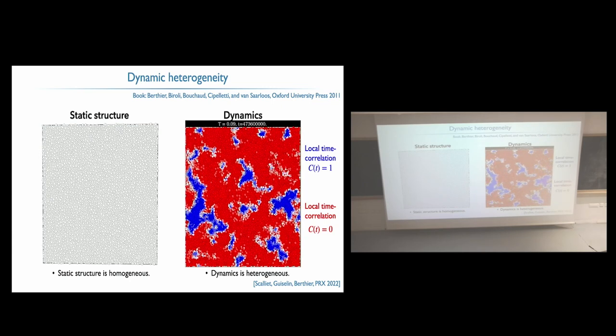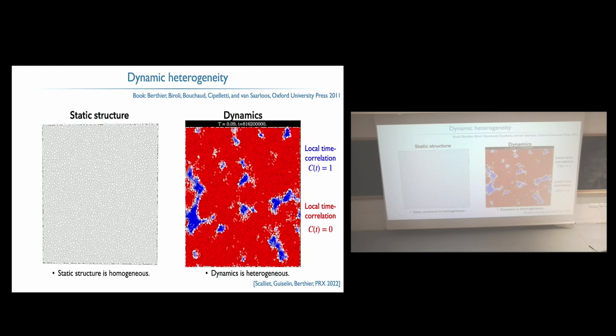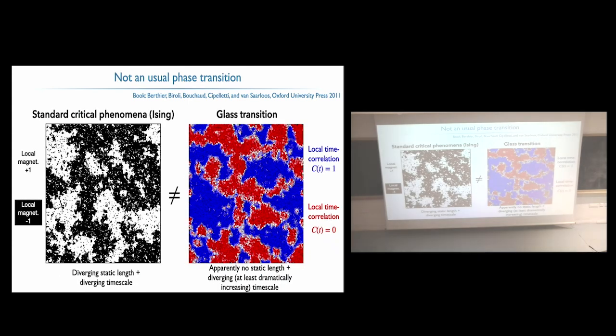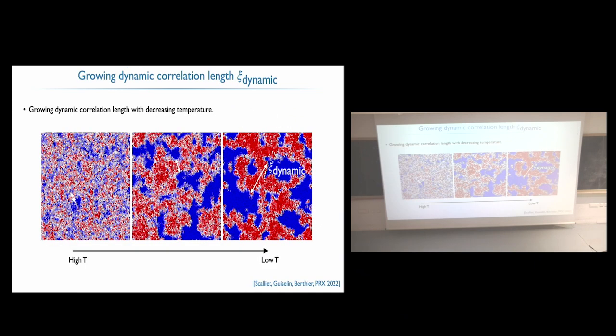You have some regions that are fast and some regions that are slow, and tau alpha is just the average of that. So you see that it's not the whole picture, but just a small part. Again, we wanted to highlight that this is an unusual phase transition, because if you think about standard critical phenomena, you look at the static structure. For example, this is an Ising configuration with plus and minus 1. You see in the static structure that there is something: a static length that's diverging, and a time scale that's diverging. This we understand very well. But here I showed you that there's apparently no static length scale, and the time scale is maybe not diverging, but at least it increases very, very rapidly. So this is very different, and we need new tools and ways to understand that.